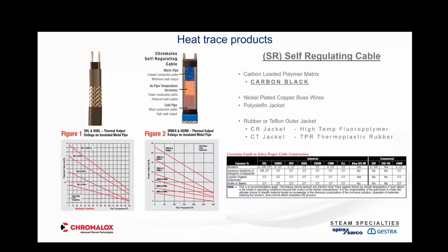And what happens is, as it sees temperature, if the pipe's hot or whatever, it expands. As it expands, it changes the actual resistive properties of the cable, which allows it to be, quote, self-regulating. So a 5-watt cable at 50 degrees is maybe a 3-watt cable at 100 degrees. Therefore, as it increases in temperature, the output inversely decreases, which gives the self-regulating properties and makes it really useful in the field for control and overheating. You can overlap it, and you can cut it.